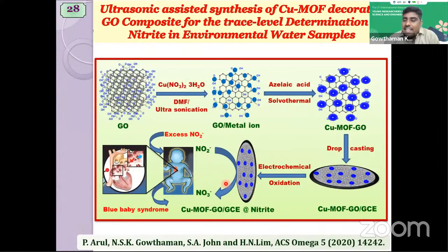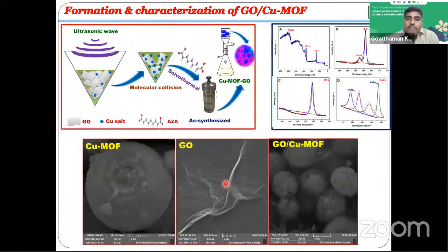The final material is the metal organic framework. We take the copper metal organic framework, decorated on graphene oxide sheets, for the detection of nitrite in environmental water samples. The synthesis of copper MOF follows an ultrasonic assisted synthesis.